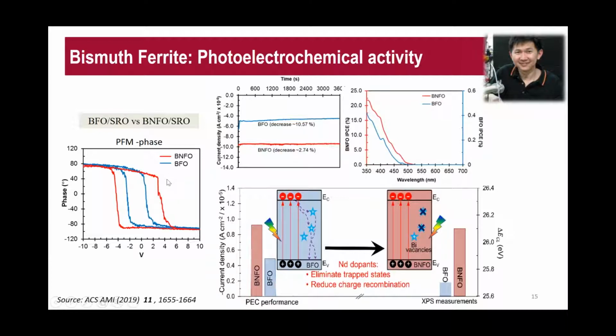So judging from here, by knowing these, we can actually explore a lot to help us understand the behavior of the BNFO in photoelectrochemical activity, indicating that having the Nd dopants eliminates the trapped states and reduces the charge recombination. So this is how we make use of the analytical tool PFM to move further on for materials selection.